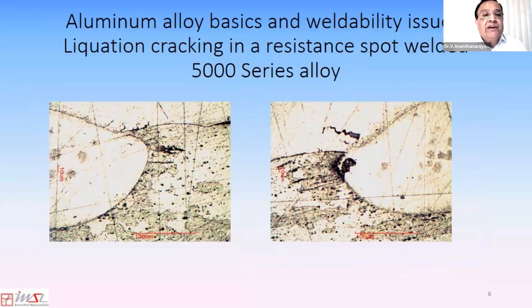And what I show here is a micrograph of a resistance spot weld of a 5000 series alloy, where these magnesium-rich second phases have cracked due to the welding heat. They have actually melted and cracked during the welding and post-weld cooling operations. So this kind of a crack obviously makes the structure not suitable for service, and it's a problem when you weld these alloys which have second phases that can cause such heat affected zone liquation cracking.